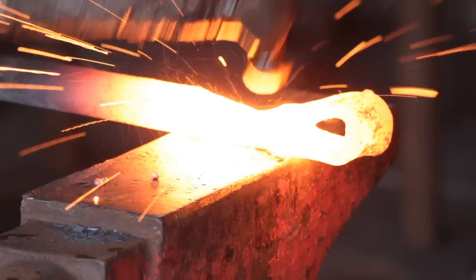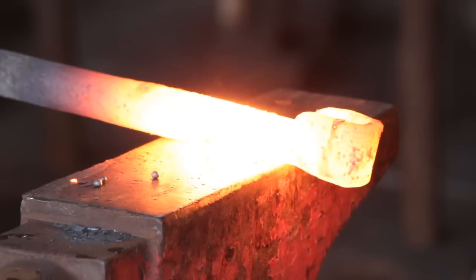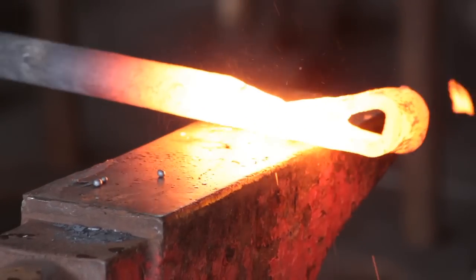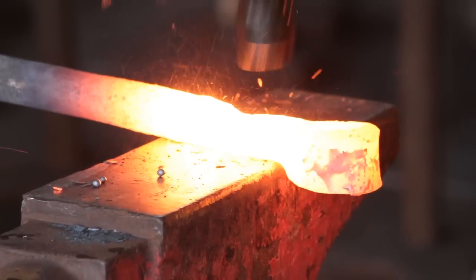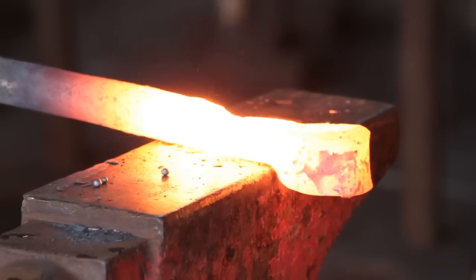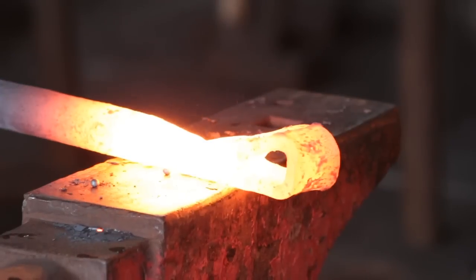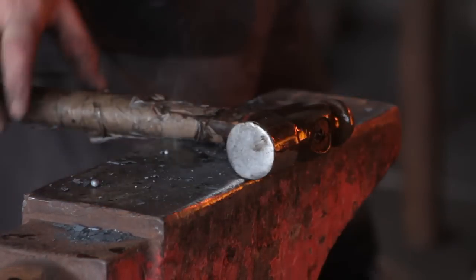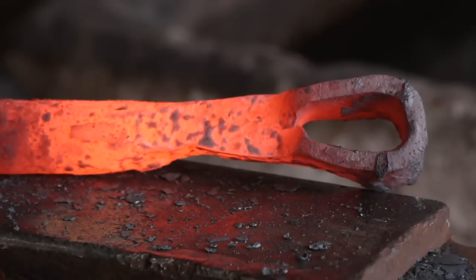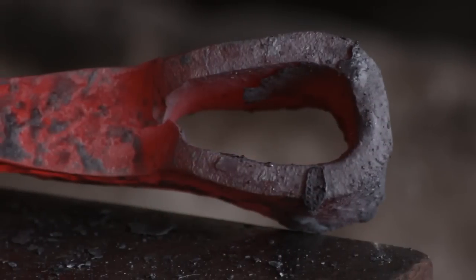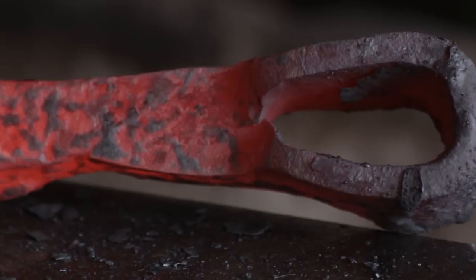Did a little bit too much blending and went a little thin right at the end of the taper. It wasn't the end of the weld, but it did mean that, and you can see there how thin that's gone, just from blending in the edges of the weld. But it's welded perfectly. It's not the end of the weld, that thin bit, I can sort that out.